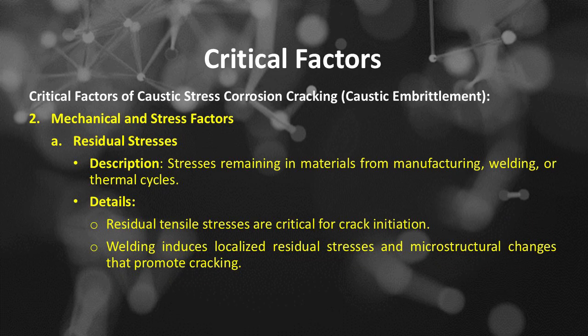Number 2 of the critical factors of caustic stress corrosion cracking or caustic embrittlement is mechanical and stress factors, which includes number A, residual stresses. Description: stresses remaining in materials from manufacturing, welding, or thermal cycles. Details of residual stresses: residual tensile stresses are critical for crack initiation. Welding induces localized residual stresses and microstructural changes that promote cracking.